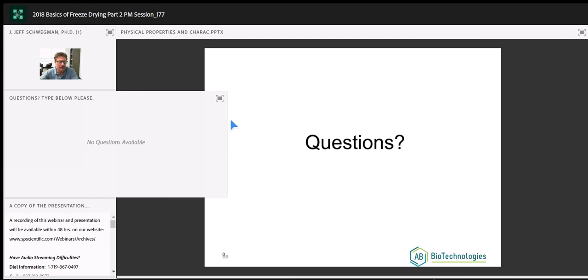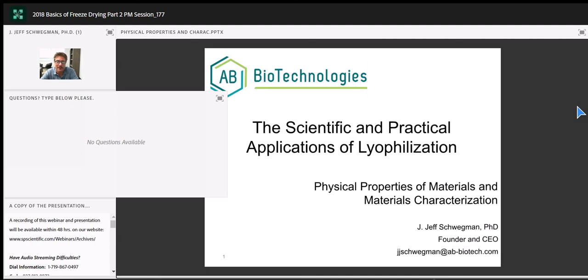Okay, so it looks like we've got a question coming through. The question is, can a vacuum pump failure during freeze drying cause meltback? The answer is absolutely. What happens if we lose vacuum in the chamber? Obviously the pressure goes up. As the pressure goes up, the heat transfer changes between the shelf and the product. This is getting a little bit out of the webinar, more for a future webinar. So product temperature will rise. As chamber pressure rises, product temperature rises until we can go through a eutectic melt, a glass transition, or actually even melt the product. So yeah, absolutely.